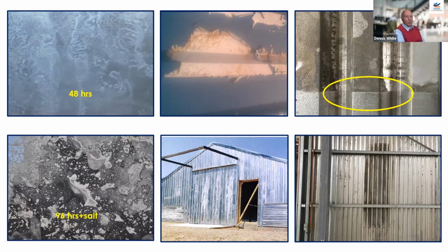So paints, when wet, become permeable. They soften depending on the time of wetness, and then the moisture breaks through to the undersurface, as you can see there in that middle photograph. On the top right-hand corner, that is some aluminium material that got wet whilst it was in storage, where the ellipse is. You can see the transition point where it was covered by a sheet above it. And the slide on the bottom shows you the type of staining you get.